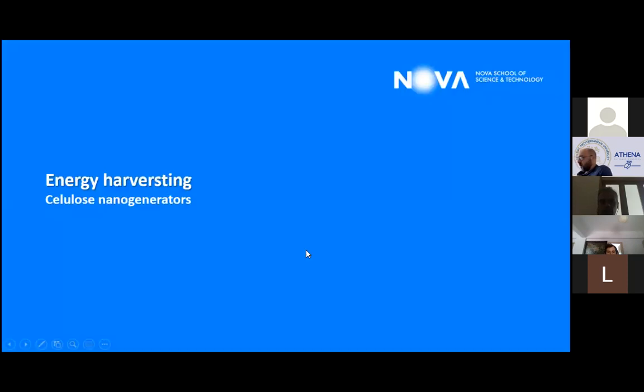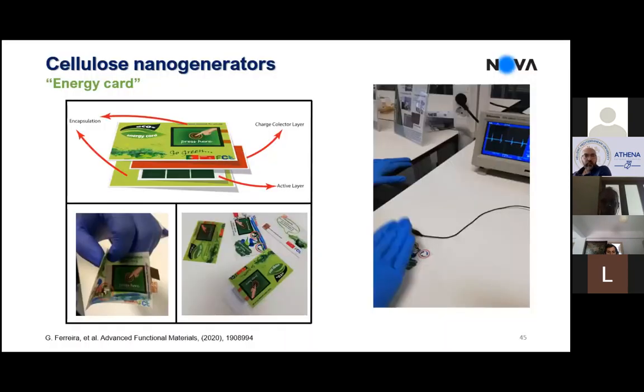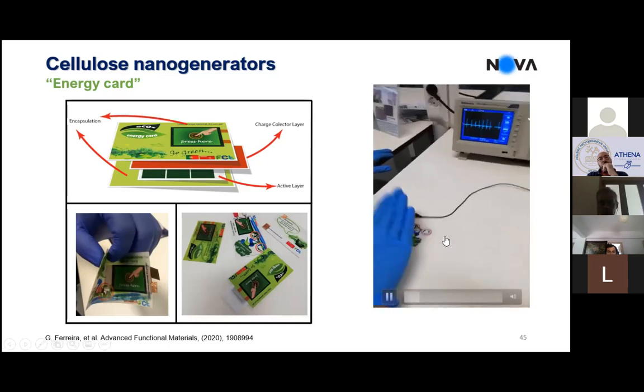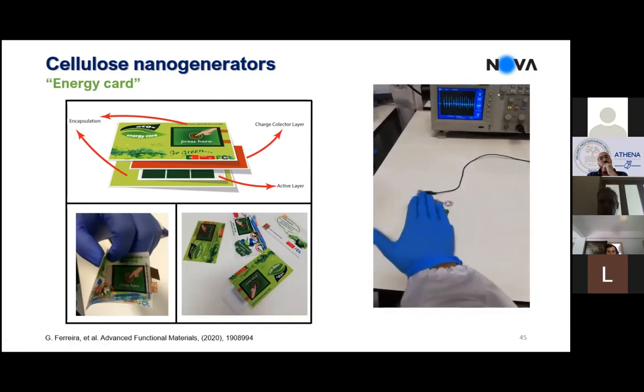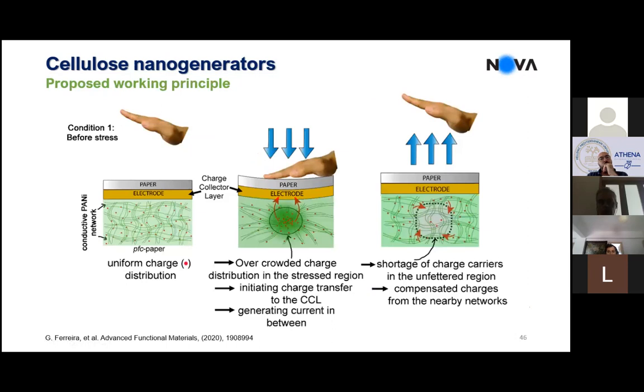Okay. Finally, energy harvesting. Let's go back to paper, and in this case, we just functionalize the fibers with a conductive polymer. The most used are polypyrrole and polyaniline, which we are using here. So we can make what we call energy harvesting cards, and I'll put a video running here, and you see the voltage being generated by just tapping on these cards. And I will show you the constitution of these cards. It's fibers functionalized with polypyrrole or polyaniline, and then you have another paper that has an electrode on it, and you have this layered structure.